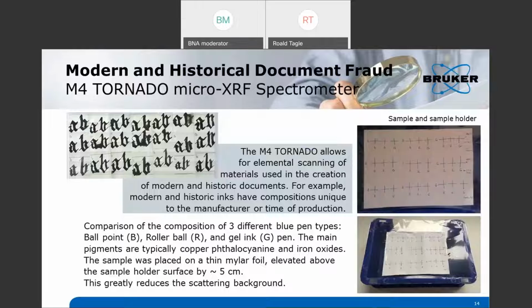We have here as a sample a sheet of paper with lines drawn with 3 different pens: a gel pen, a roller ball, and a ballpoint pen. So we can scan this piece of paper and do an elemental analysis. In order to minimize the background, we elevated the paper slightly above the base by putting it on a mylar foil in a box which is roughly 5 centimeters high. So we get much less scattering from our acrylic table, or in this case the bottom of the box, and therewith a better signal to background ratio.